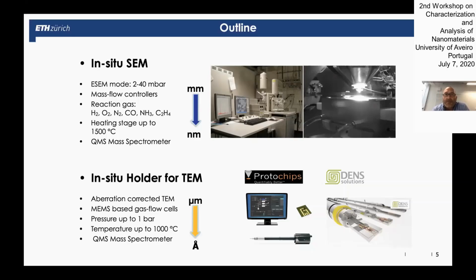And there are lots of collective dynamics, also some of which I will show tomorrow in my presentation, some collective dynamics that involve the transport of many, many atoms, and often also fast transport of many atoms, and things that are related to heat and diffusion, for example. And such processes are difficult to study at atomic resolution. So for this, actually, it is quite a good idea to correlate observations in the TEM with observations that you do at lower magnification, for example, in an SEM.